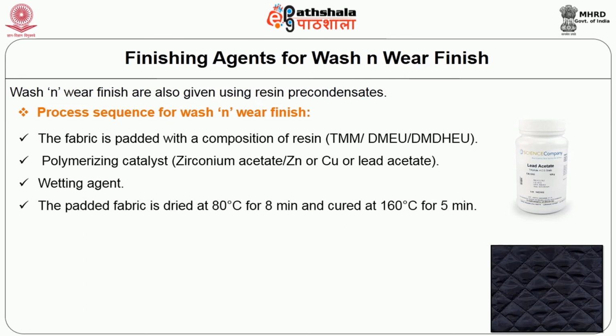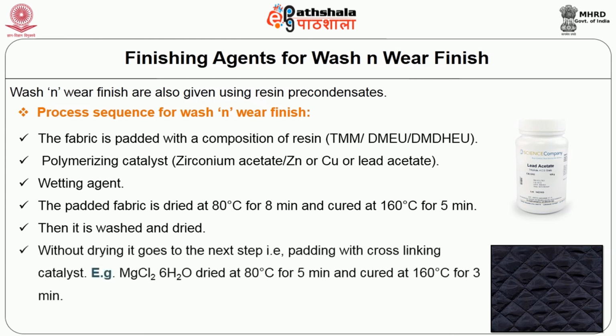The padded fabric is dried at 80 degrees centigrade for 8 minutes and cured at 160 degrees centigrade for 5 minutes. Then it is washed and dried. Or without drying, it goes to the next step, that is padding with cross-linking catalyst, example magnesium chloride, dried at 80 degrees centigrade for 5 minutes and cured at 160 degrees centigrade for 3 minutes. It's given hot rinse, cold rinse and dried.